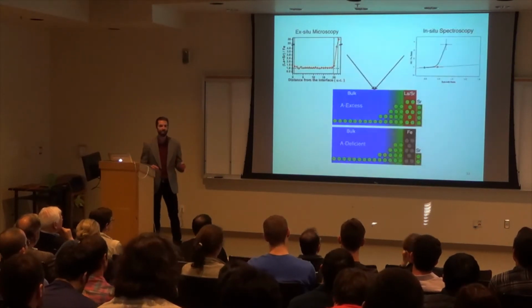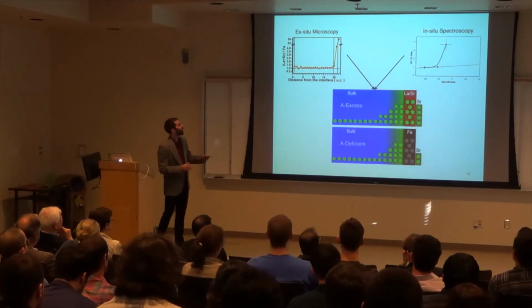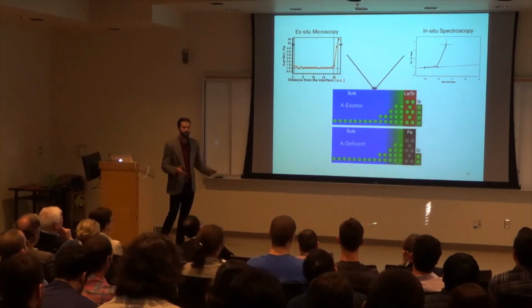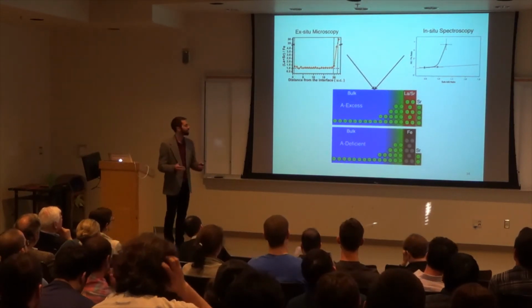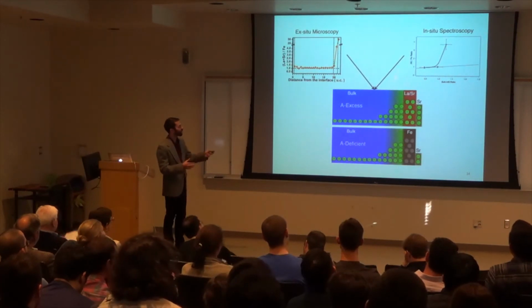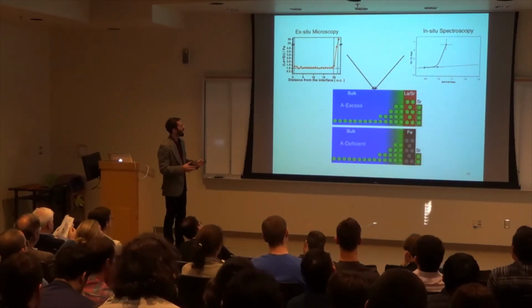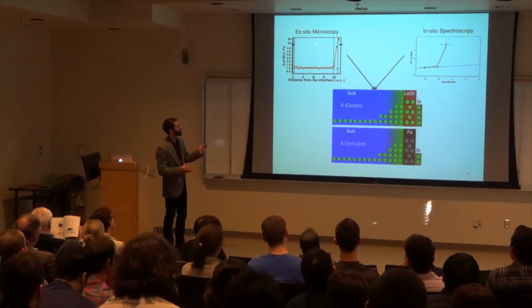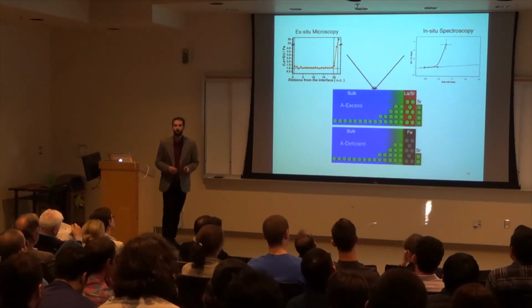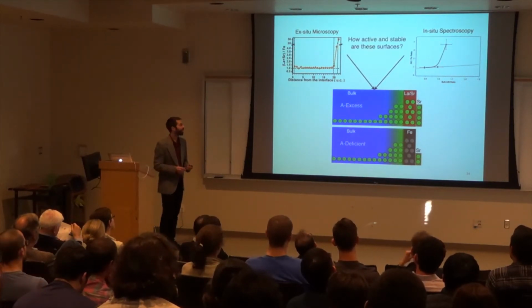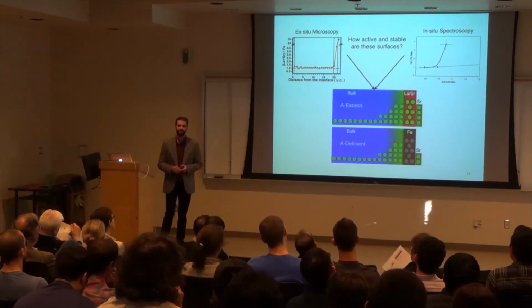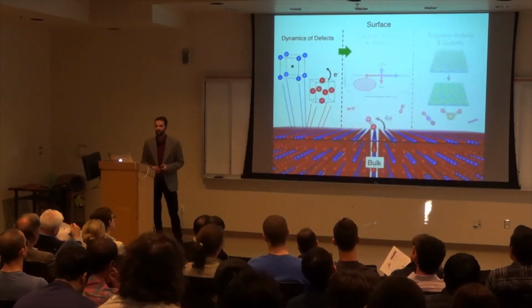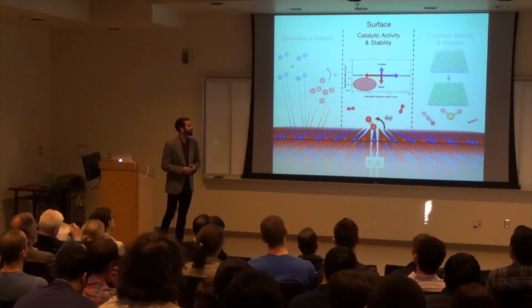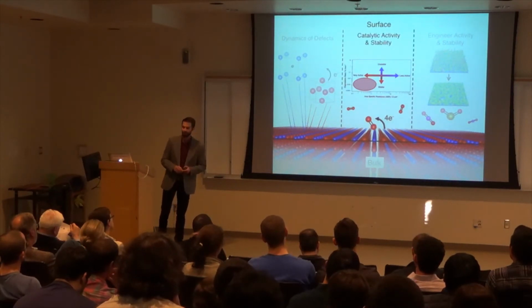So to summarize what I just talked about, we've basically seen that as we change the bulk composition of the material system, we can change the surface termination. And we've confirmed this with ex-situ microscopy and in-situ spectroscopy. But now this begs the question, how active and stable are these surfaces, now that we know what's on them? So to that, we now turn to measuring the activity and the stability of these films.